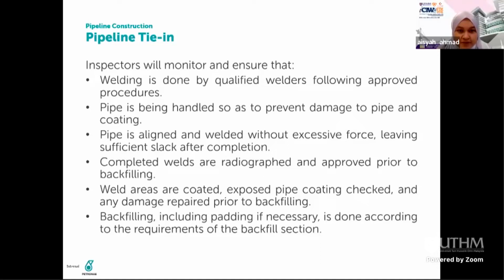Complete welds: how do we ensure that the welding is okay? Usually we use radiography on the completed welds, and we need to ensure there are no defects in the welding, and the welds need to be approved prior to backfilling. And all the weld areas are coated.